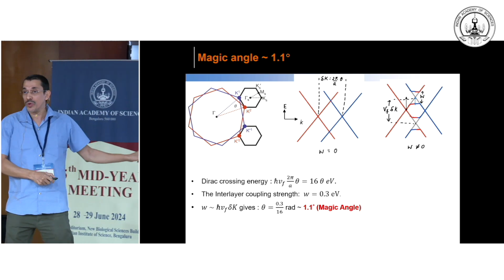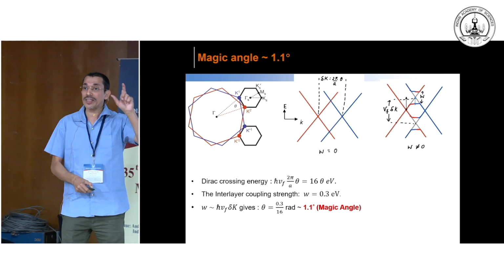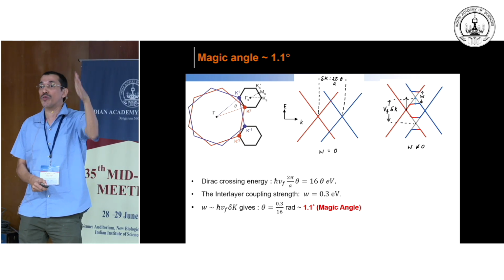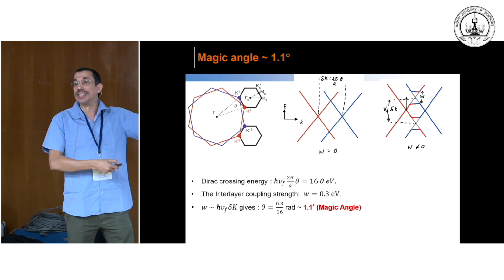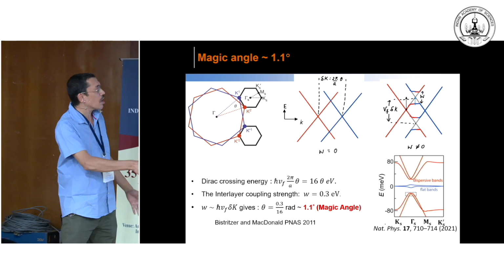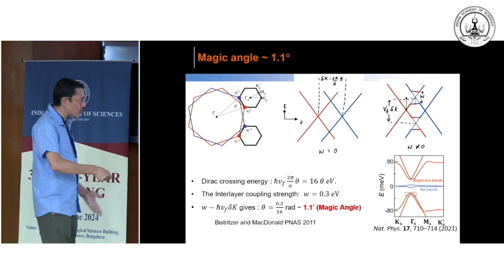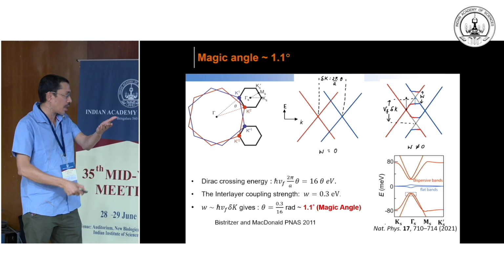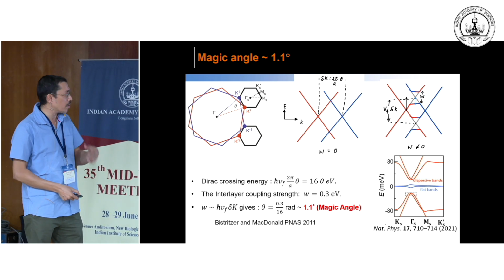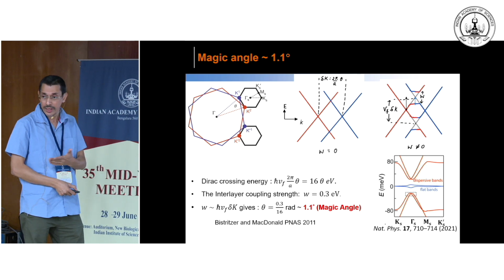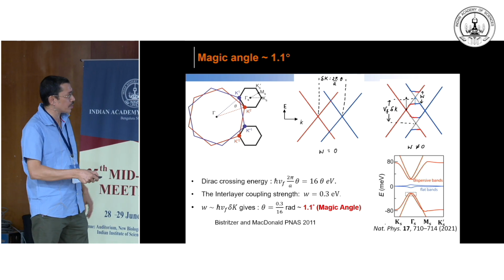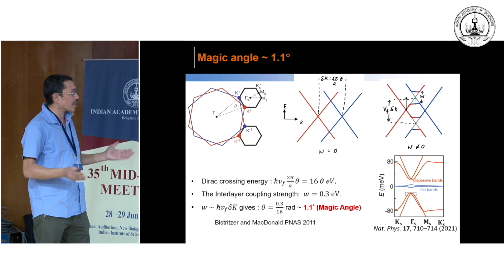So that tells you that exactly 1.1 degree is something special or unique that happens, which is known as the magic angle in this kind of system. And this has been shown in a continuum model, and in fact there are many tight binding calculations, in which Manish and Sinjon have been involved, and H.R. Krishnamurthy, even with relaxation and without relaxation.